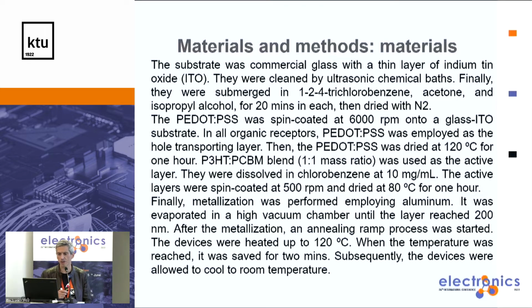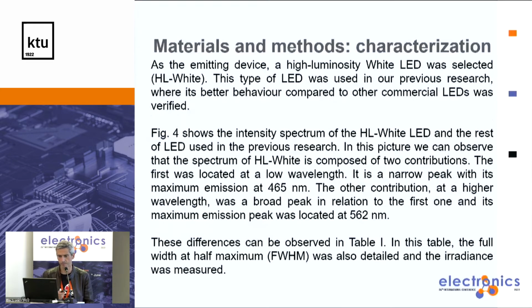Finally, metallization was performed employing aluminum. It was evaporated in a high vacuum chamber until the layer reached 200 nanometers. After metallization, an annealing ramp process was started. The devices were heated to 120 degrees, and when the temperature was reached, it was held for 2 minutes. Subsequently, the devices were allowed to cool to room temperature, about 25 degrees.